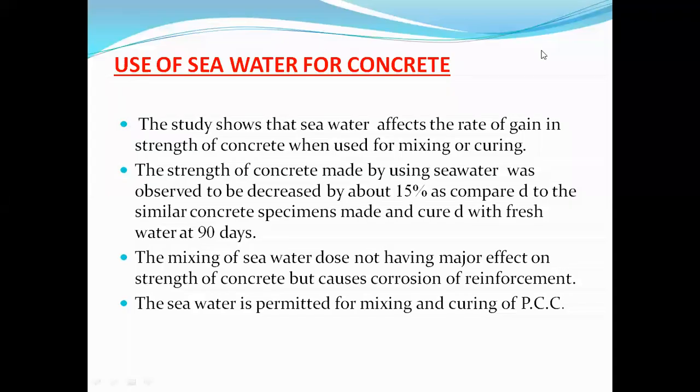Point number two: the strength of the concrete made using seawater was observed to be decreased by 15% as compared to a similar concrete specimen made and cured with fresh water. That is, the concrete made and cured with regular water has greater strength as compared to the concrete made with seawater. There is a decrease in strength of about 15% when we use seawater for the concreting work.